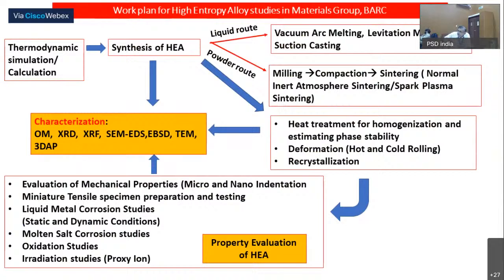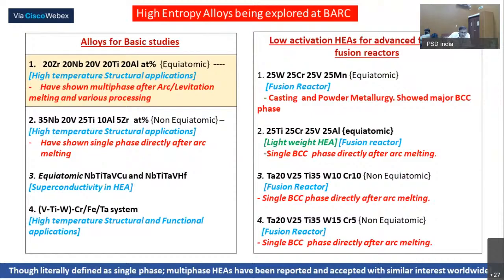We have done a lot of thermodynamic calculation, some simulation work, and based on that we arrived at certain compositions. Then we synthesize the alloys by vacuum arc melting, levitation melting, suction casting, or powder metallurgy route, and then do exhaustive characterization to figure out what is happening. And in this process, we did some of the work.